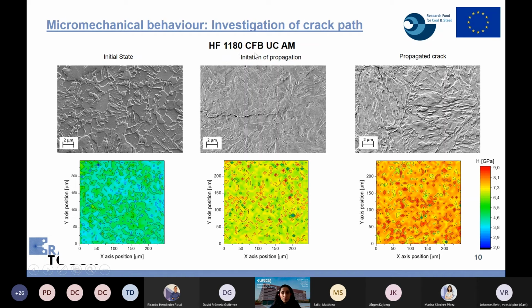In the CFB grade steel, the microstructure basically consists of a bainitic matrix with martensite islands, and I want to point out the arrangement of the bainite laths. You can see that these laths are linear and elongated. So this leads to a needle-like morphology of the retained austenite. This is important because in this last image, where the crack is propagated, the crack follows these laths of bainite and also follows the needle-like morphology of the retained austenite. So the crack is along the bainitic grain.